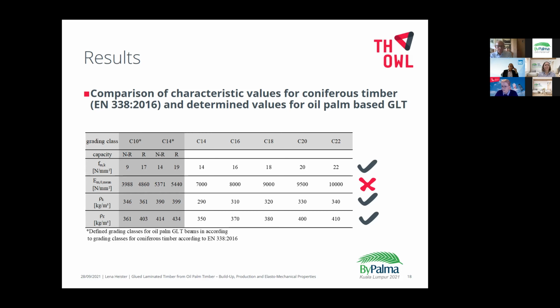The characteristic stiffness values for coniferous timber are not achieved with GLT beams made of oil palm timber. The values for the average density and the characteristic density for oil palm beams meet the requirements of the standard. Finally, it remains to mention that the ratio between MOR and MOE for oil palm is significantly lower compared to the ratio for softwood.